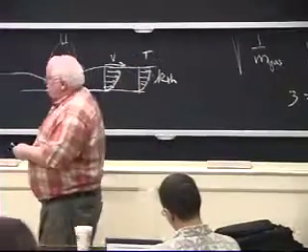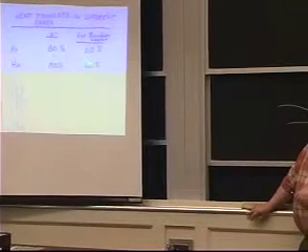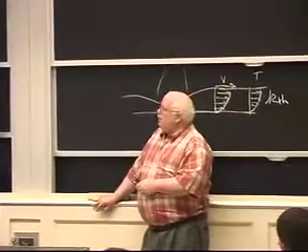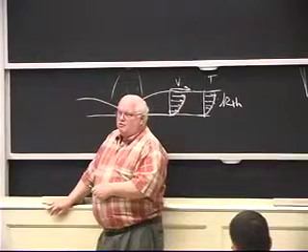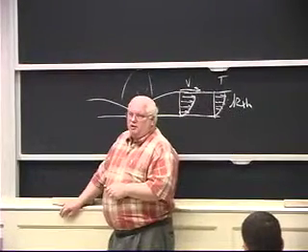So if in an argon plasma, 20% of the heat is going across from the conduction, the thermal conductivity of the gas, then in helium I'm going to get 3 times as much. So if my total normalized heat for argon is 1 or 100%, helium is going to give me 40% more heat transfer because of the thermal conductivity across the gas boundary layer.